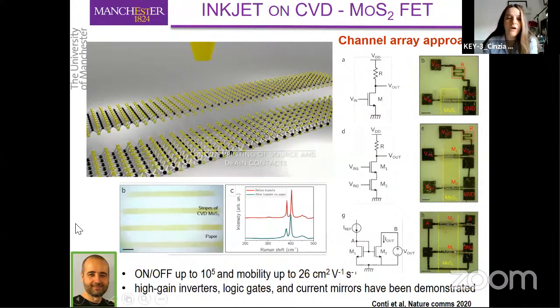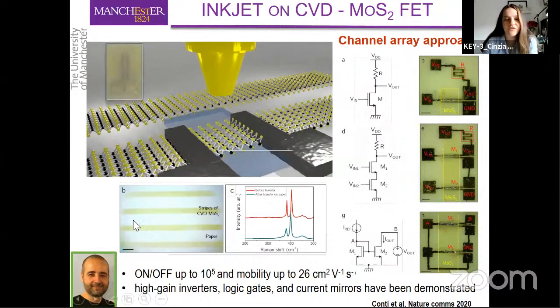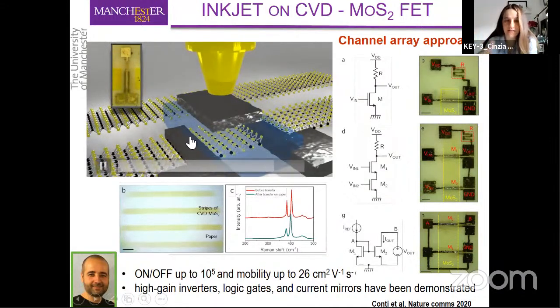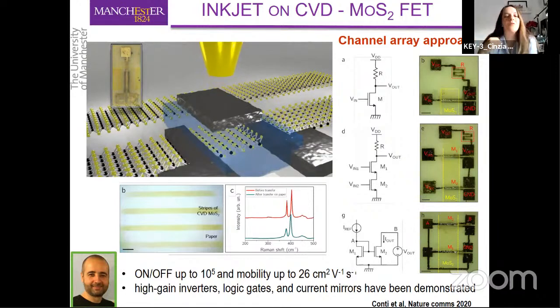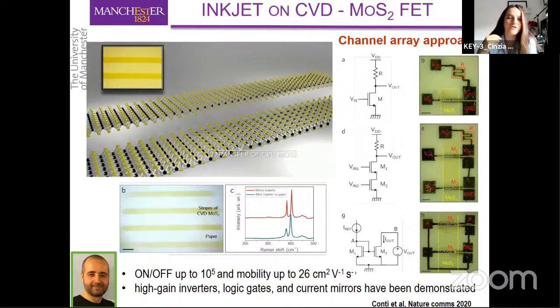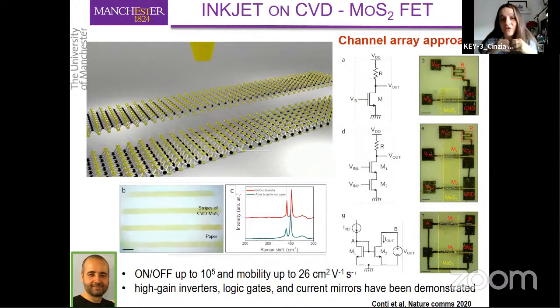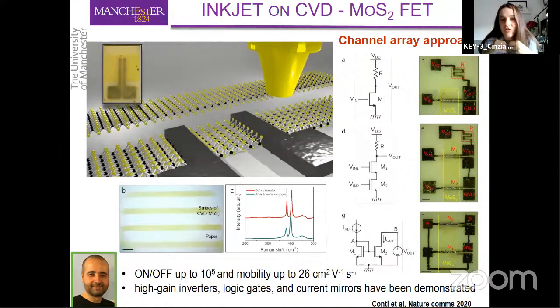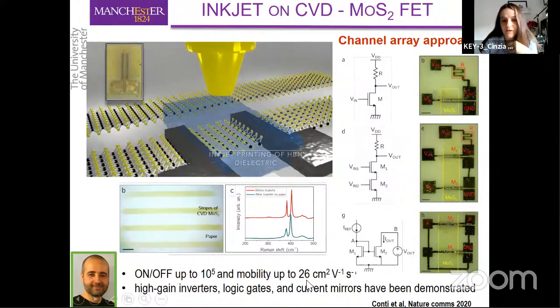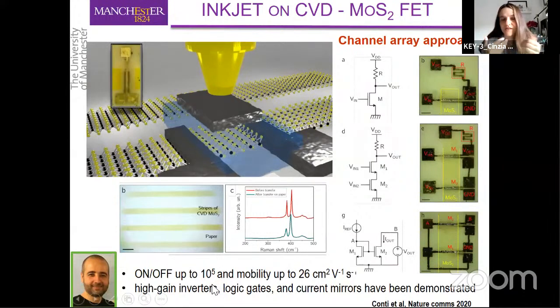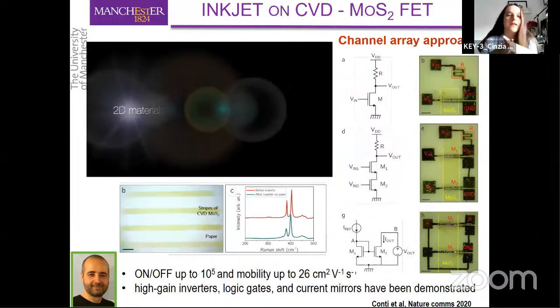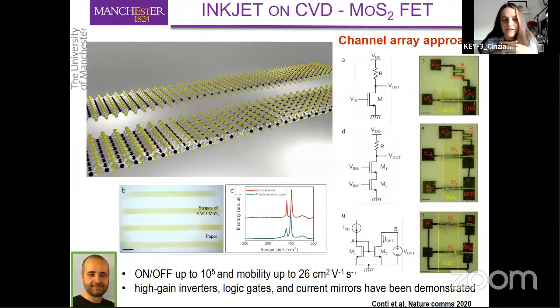And so what we did in this work was to pattern the CVD molybdenum disulfide into stripes and transfer them onto paper, as you can see in this picture here. And then the rest of the device, the electrodes, the dielectric and the top gate, were done using boron nitride and either silver or graphene inks. And to our surprise, it turned out that the fabrication of the device on top of this very high quality channel actually does not affect the electronic properties of the channel. The mobility is still very good, and the on-off ratio is still very high, and basically those values are comparable with the same mobility and on-off ratio that one would find by making the same transistors by standard lithography.